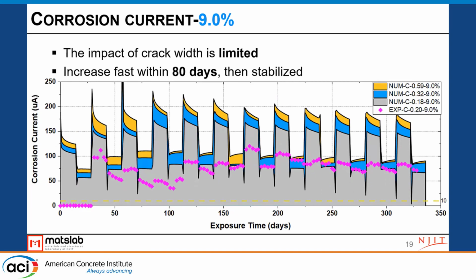And the 9% one. So what we really want to figure out is the impact of crack width. From this series of simulations and tests, we can observe that the impact of crack width itself is limited, because when we have an initial crack of 0.18, we see a significant amount of corrosion. However, when we increase the crack width, the corrosion itself is not increasing proportionally.